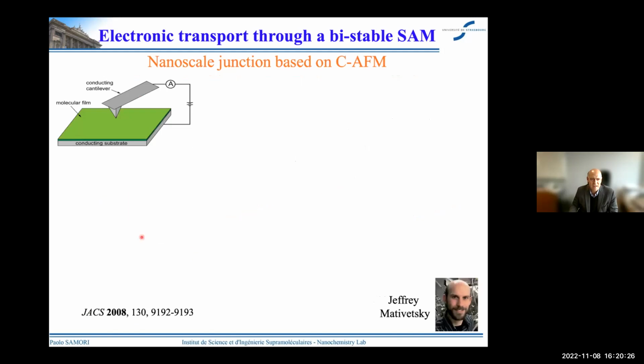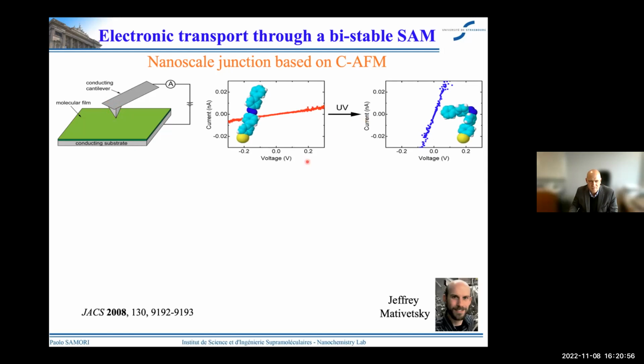And therefore, I decided to perform the first experiment and to demonstrate that you can have a vertical junction based on conducting AFM, in which you have a gold conducting substrate that is covered by a self-assembled monolayer of our molecule, and use as a counter electrode a metal-coated tip of an AFM. And we have been studying the light responsive electrical characteristics of this monomolecular junction. You can see that when the molecule is in a more extended trans form, the currents are weaker, here in red, whereas when the molecule adopts the cis conformation, there is a much higher current in the junction.